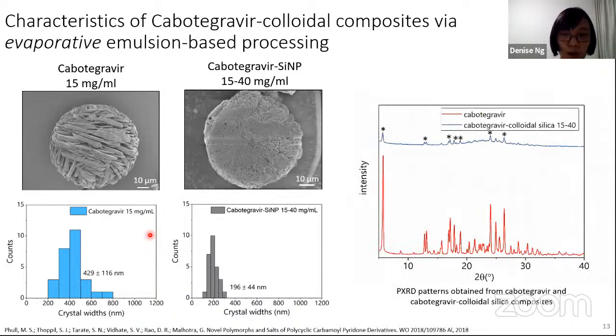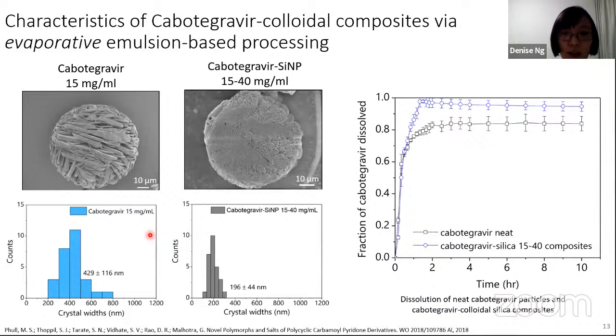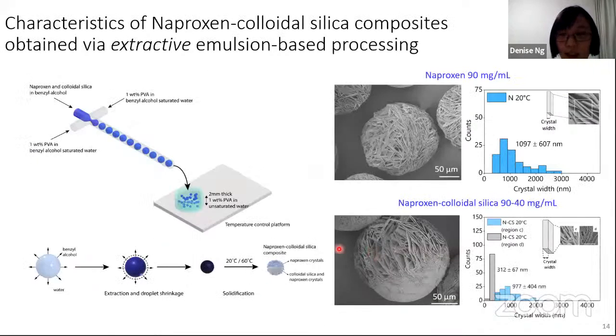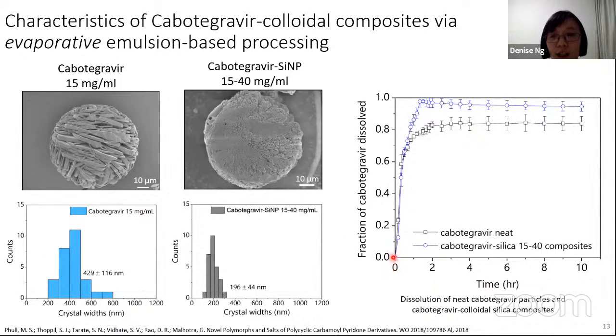We then proceeded to look at the polymorphic outcome, and we observed that both the neat cabotegravir as well as the composite case are of the same polymorphic form, which is form C1. And with this, we can study the dissolution, as any changes in the dissolution can be directly correlated to the differences in the crystal dimensions. Here, in the case of cabotegravir, we observed that our composites can dissolve to a much greater extent as compared to the neat case. And this suggests potential in implementing it to address the dissolution extent of hydrophobic drugs.